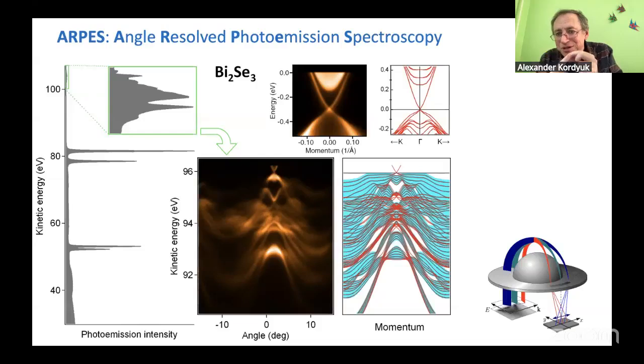around the Fermi surface. If it's not topological, then all the states are degenerate in spin, and from each state it could scatter to another state at the Fermi level. But if it is topological, then at each other state you have a different direction of the spin, so you have at least half of the states fewer, roughly, and therefore it is much more stable. But from the topological point of view, I understand that this band should be there anyway, of course, and it should be stable. But we just could not see it. It is just a different disappearance.